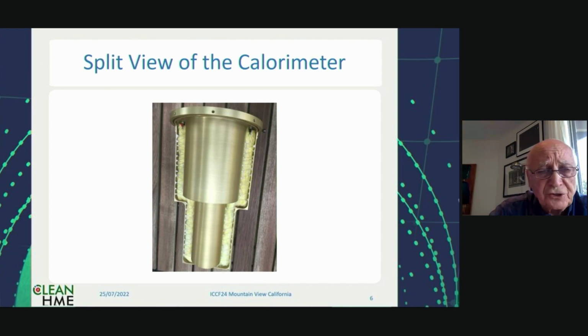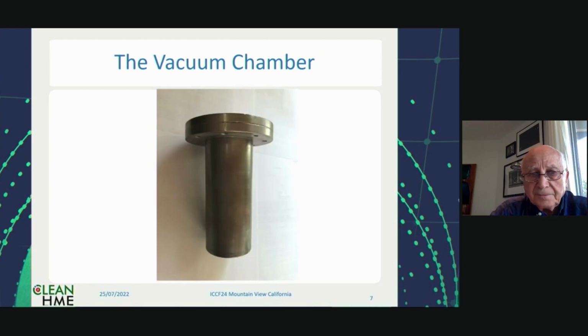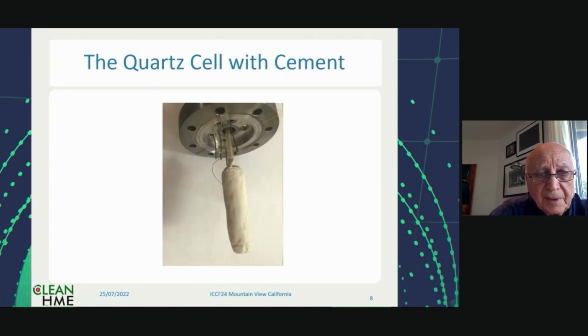This is the construction of this calorimeter, where you can easily see the 50 thermocouples that are glued by cement on both sides of the two aluminum cylinders. Next slide. This is the vacuum chamber I was talking about, 150 millimeter by 63 millimeter in diameter. Next slide. This is one of the quartz cells, where you don't see the inside, but there is a Kanthal wire and there is a cement on top to isolate it. Next slide.